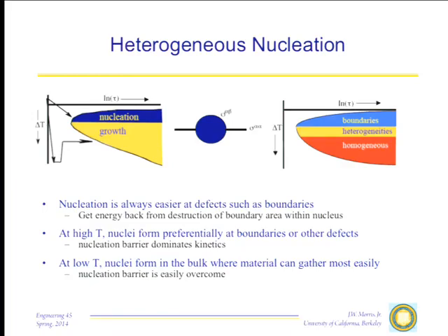An important reason for doing that, and that's the third interesting feature of this nucleation and growth behavior, is that the mechanism of the transformation, the pattern of the transformation, changes depending on where we are on this curve. In most materials, when we're up at the top of the curve here, the kinetics of the transformation is dominated by the difficulty of nucleation. That means that the transformation will occur preferentially at those sites where nucleation is easiest. And these are the heterogeneous sites, such as grain boundaries in a polygranular material or dirt particles in a glass of beer or whatever. And so you can control where the transformation happens up in this region by, for example, artificially introducing a group of nucleation sites.